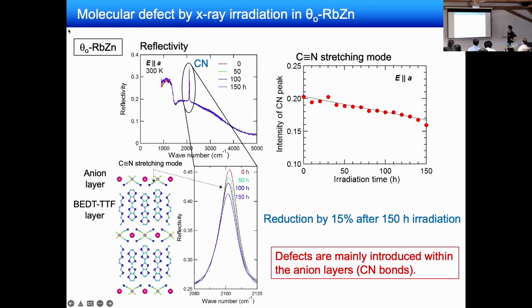But if you look at the entire spectra, which comes from the BEDT-TTF pi electron system of BEDT-TTF, there is no difference with irradiation time. This indicates that molecular defects by X-rays are mainly introduced within the anion layers, not the BEDT-TTF layers.